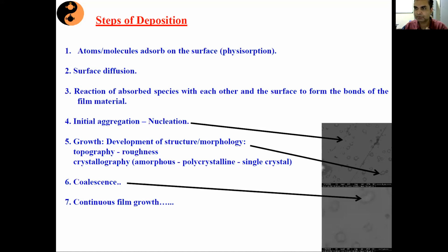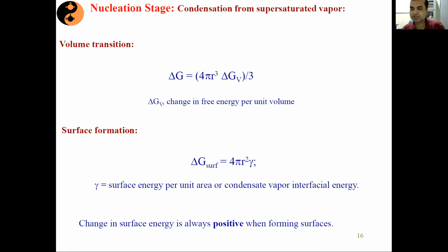Number one. Number two, can any nucleation be stable and give rise to thin film growth? The answer is again no. Not all nucleation is going to be stable. For any nucleation to be stable, there has to be a finite size of that nucleation. If that finite size is not available, then this nucleation may be unstable, and then again they will break into pieces, and those evaporants can again get dissolved back into the atmosphere. So we'll try to understand what are those conditions under which those nucleations can be stable.